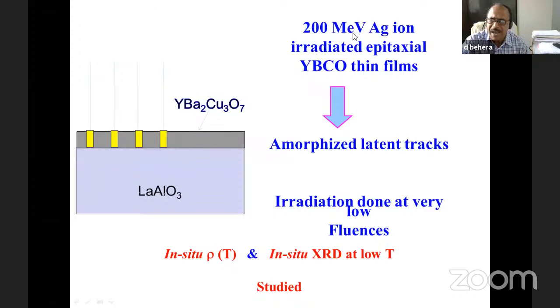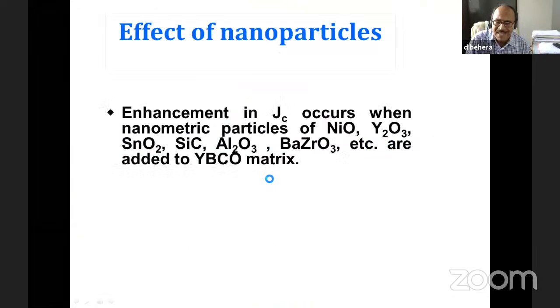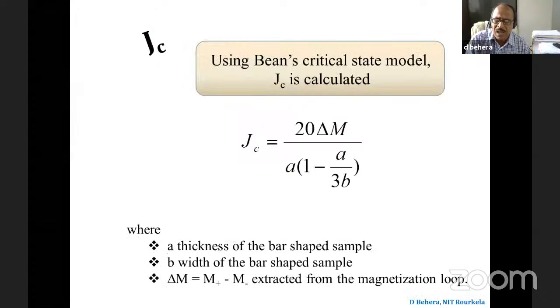it was irradiated by 200 mega electron volt silver ions. You see the high energy. Silver ions were irradiated on the epitaxial thin film, and in the process we create defects. You see, over a centimeter of this material, we only create some nano-order defects, and these nano-order defects can be used for enhancing the critical current density. So these are the effects of nanoparticles in nanomaterials. And we measure the critical current density by measuring the change of the magnetization by the SQUID.